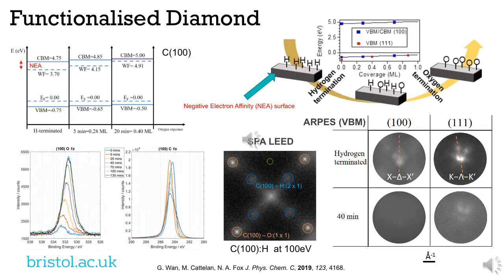We were able to show that it's possible to modulate the work function and band structure of diamond by a simple control of oxygen adsorption on a hydrogen terminated surface and determine the relation between oxygen coverage and electronic properties.